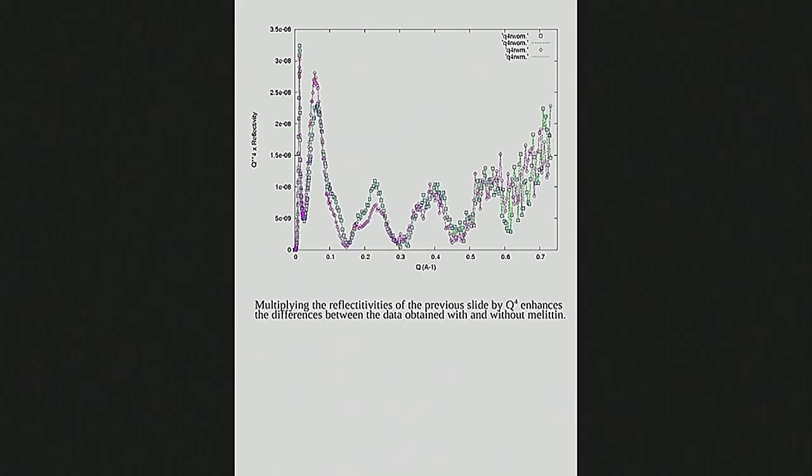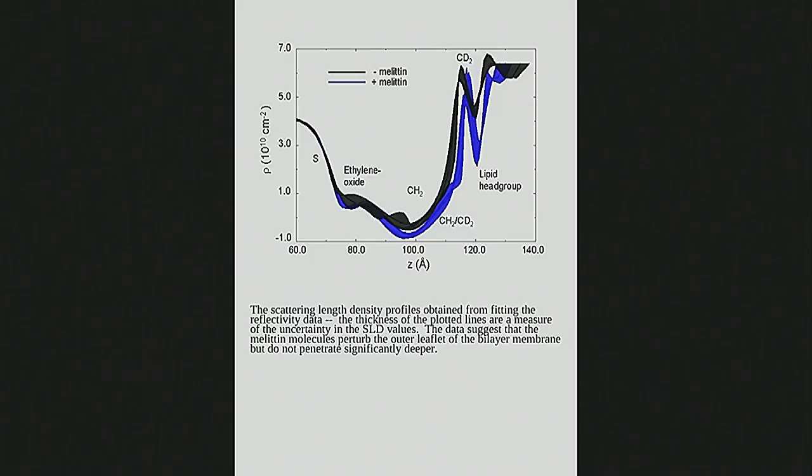And if you numerically analyze that data, solving those simultaneous equations in that piecewise continuous solution fashion, you find, the gold isn't shown in this particular plot, just the two leaflets of the bilayer, that the melittin resides only in the vicinity of the head group. It sort of penetrates into the head group, but it's absolutely clear that it doesn't extend into the head groups at the bottom or very much into the tails at all.